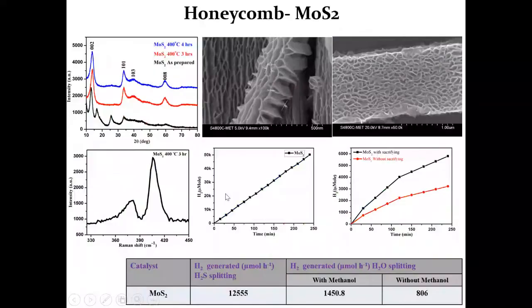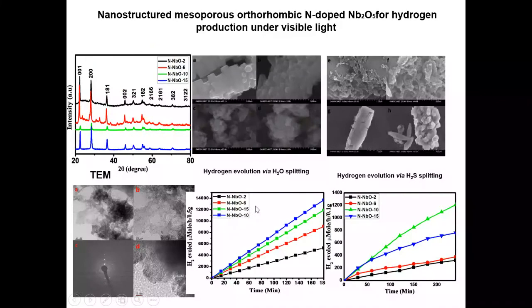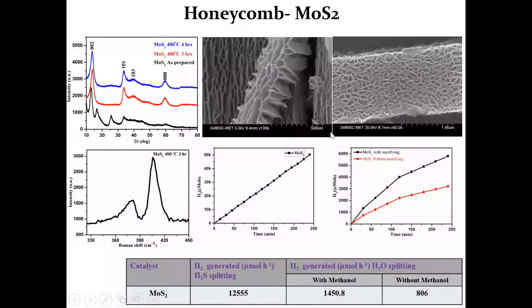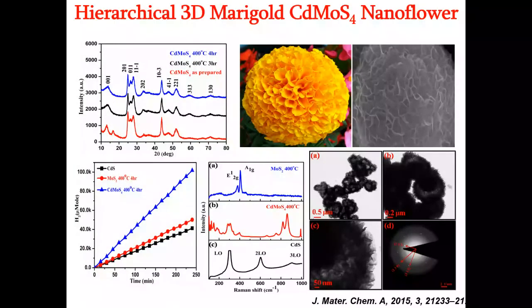Here I have given different nitrogen percentages, and at optimum nitrogen doping we get good hydrogen production. This honeycomb-like structure is MoS2. See the structure of MoS2 we can synthesize. It is very much like a honeycomb. Because of this pore structure, we get good photocatalytic activity and hydrogen production. You see, we observe linear hydrogen production. Then we combined cadmium and molybdenum together. The structures are flower-like, and you see porosity is increased. It also gave good photocatalytic activity.